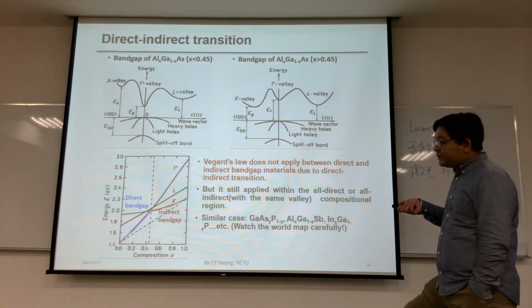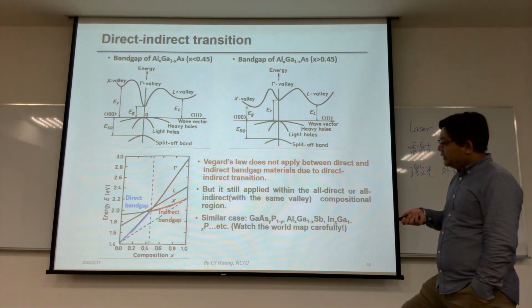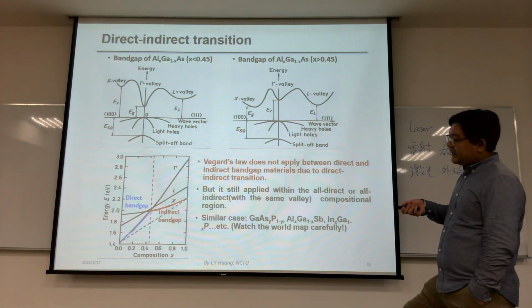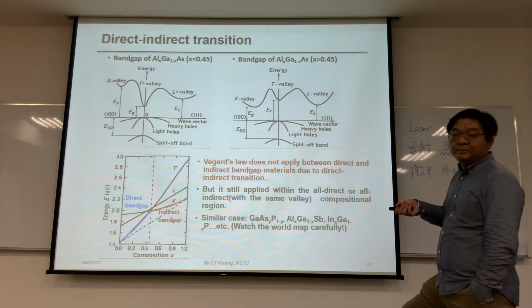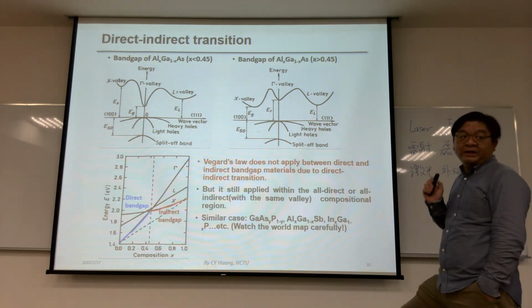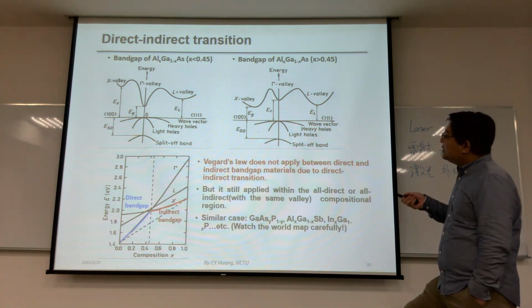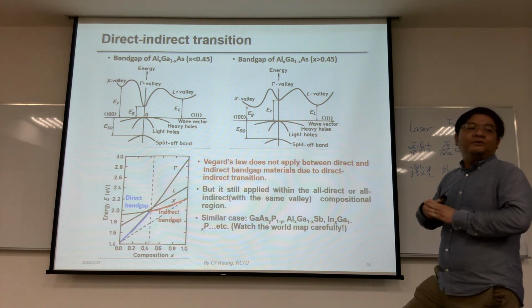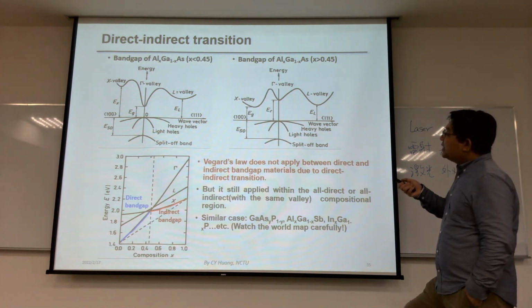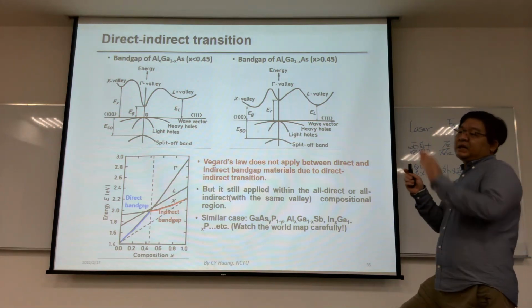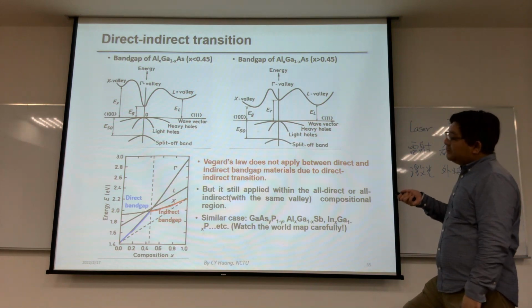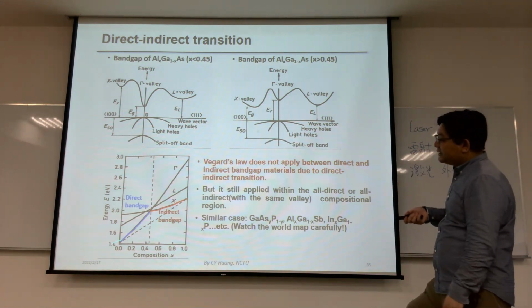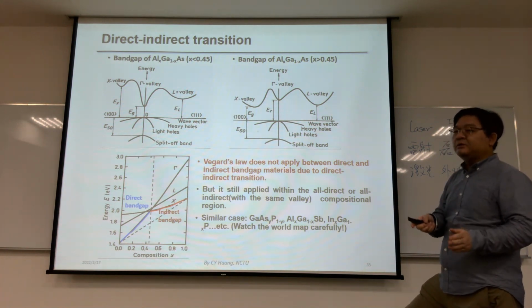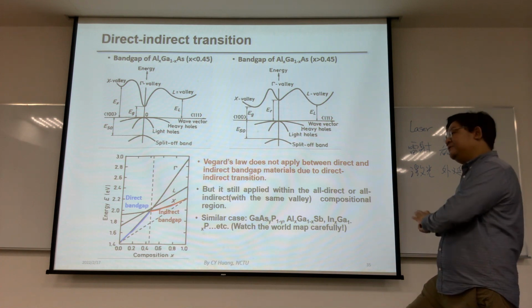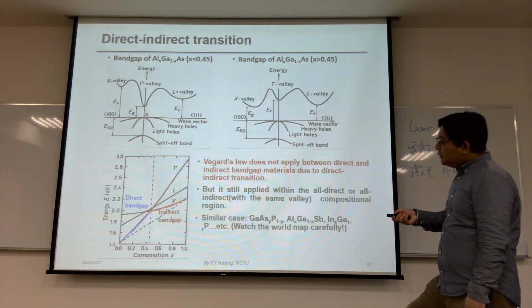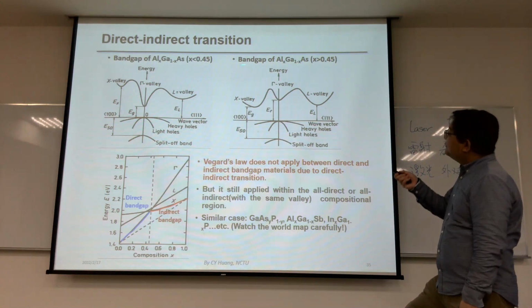So if you directly apply Vegard's law between gallium arsenide and aluminum arsenide, your composition is along this line, the black dashed line. Surely you will get the wrong answer. So it is actually important to record the crossover of the two valleys. We call this the direct-indirect transition. That means that beyond this position, the energy minimum is set by the other valley. So it changes from a direct bandgap material to an indirect bandgap material, or vice versa. For aluminum gallium arsenide, this position is 45%.